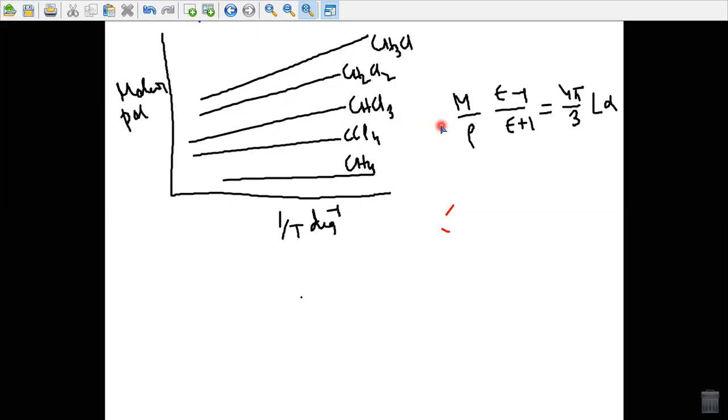I repeat, this is a very important observation: in the absence of thermal agitation and interactions among themselves, molecules with permanent dipole moments would all line up completely on application of an arbitrarily small electric field, so that the dielectric constant would be infinite, which is a fallacy. Actually the orienting tendency of the electric field is partly compensated by the thermal agitation, and in solids and some liquids, the orientation is hindered by close range mutual interaction of the molecules.